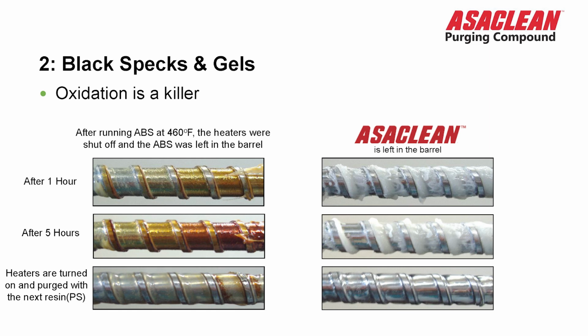On the right side, where you use the Asaclean that's left in the barrel, the top photo will show you that the ABS is completely gone. After 5 hours, obviously, there's nothing happening whatsoever. In the last frame on the bottom, you'll see that once the Asaclean is displaced with, in this case, polystyrene, the screw is like it came out of the box, free of contamination.